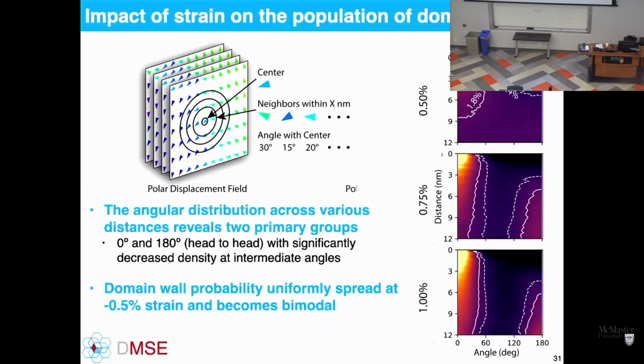You have largely correlation at a very local range. As I go further and further out, that correlation falls off to sort of a constant level, meaning as I go down here, I can get any polar direction. That's why that's purple. As I go towards higher and higher strain, I only get two configurations, basically, that we have 180-degree rotation between two domains. That's what we're seeing in these maps, and we can basically measure correlation length.